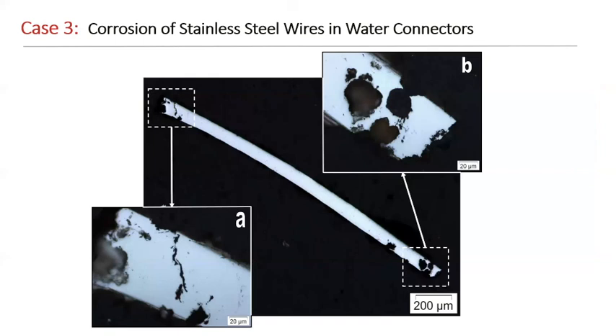Here, the cross section. So we mounted and polished these wires to show how the cracks and the pitting progressed inside. And we basically show that there were some fine cracks and pits that weakened the materials and eventually led to the failure. And obviously, as you can see, there's not a whole lot of material loss due to surface corrosion. The corrosion itself was just very rapid, very invasive, going into the material itself. And in this case, the root cause of this type of corrosion was stress corrosion cracking aided by pitting. And it points to the wires being attacked by chemicals, which caused the breakdown and the starting of the pitting and the stress corrosion cracking.